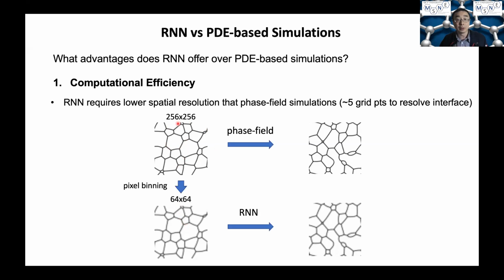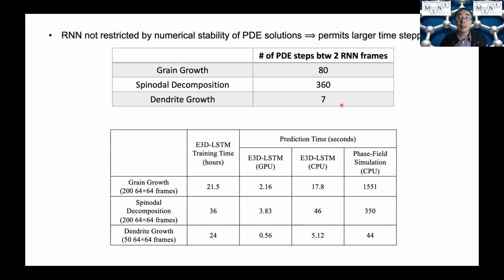And this is actually exactly what we did in the grain growth prediction. So we run the phase field simulation on the 256 by 256 domain, and then downsample the data to 64 by 64 domain to represent the polycrystal structure. And then we use such downsampled data as the training data to train the RNN models, and then we make predictions. And you can see the predicted structure in this coarse grid actually has very good agreement with the phase field simulation on the finer grid. So that's one aspect of improving the computational efficiency through spatial coarsening. And another type of coarsening is temporal stepping coarsening.